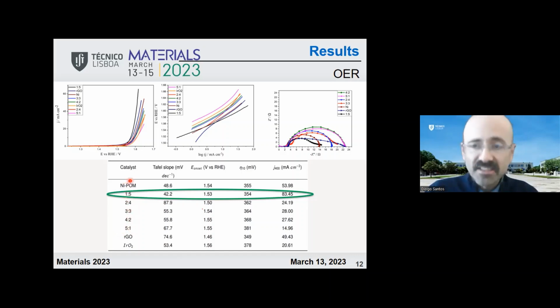And preparing those different ratios, we could try to assess what was the best composition for these materials. And what we could see here was that, of course, we also tested just the nickel POM without the RGO and just the RGO without the nickel POM. And it was very interesting that the material with the best performance was this 1 to 5 nickel POM, well, 1 part of nickel POM to 5 parts of RGO. It had the lowest Tafel slope.